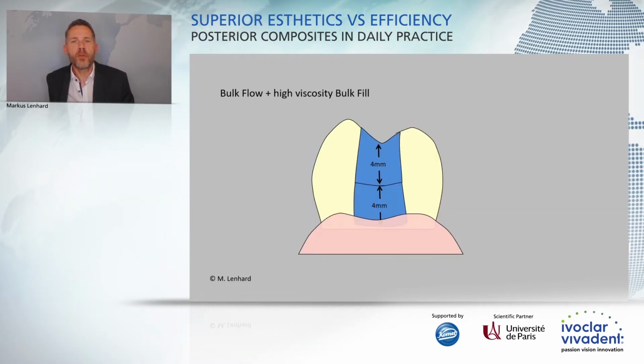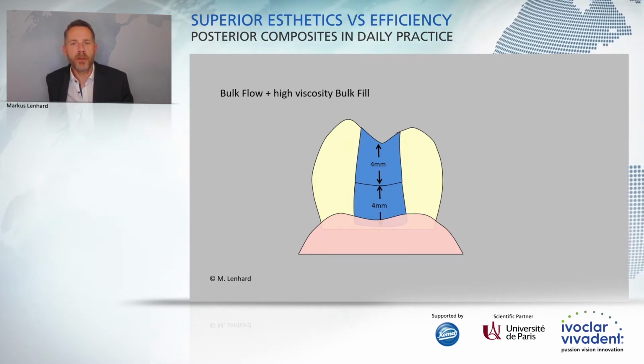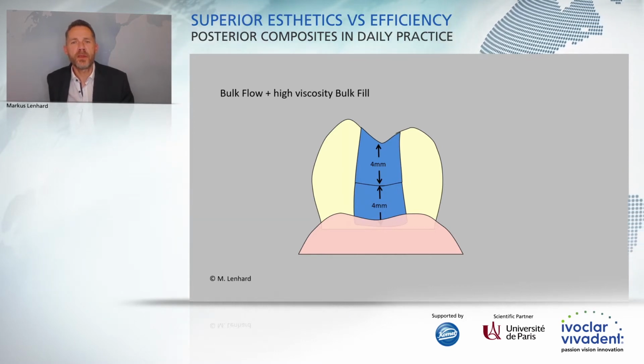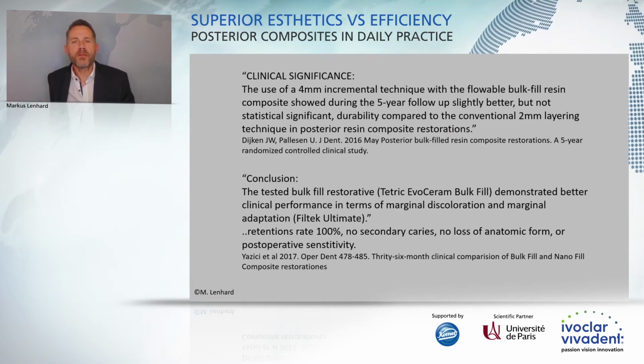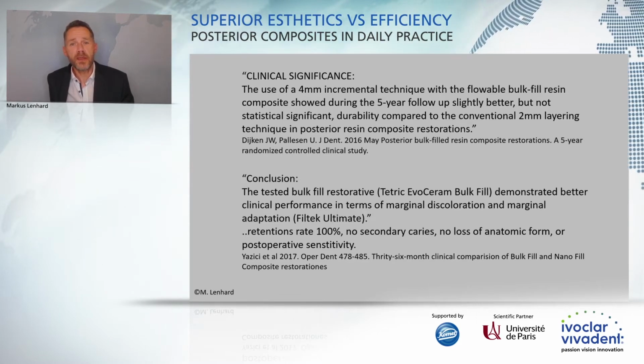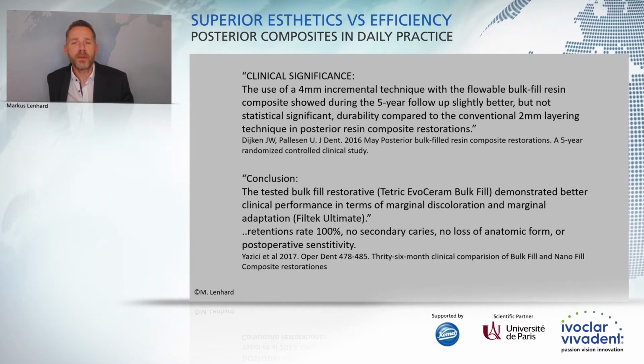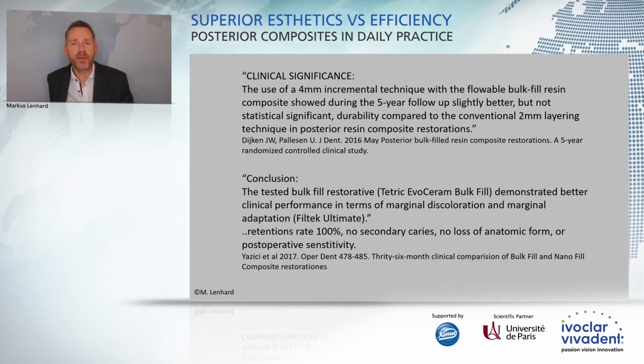And of course, you could combine these two approaches in the depth of the cavity using a flowable bulk fill material in layer thickness up to 4 mm, and on top you use a high viscosity bulk fill, which then gives you the fastest and easiest procedure in restoring a cavity. When we look at the results of these materials, we will find that in vitro studies and even the clinical studies show that there is no difference in the bulk fill restorations compared to conventionally layered restorations.